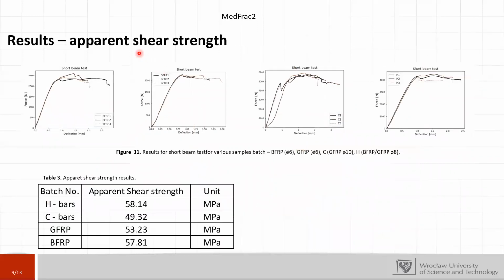Moving on, the results for apparent shear strength. So we see four graphs with the results for a different specimen batch. Here we have the basalt fiber, then the glass fiber, and here it's for the C. It's also a glass fiber, but with the greater diameter, 10 millimeters of diameter, and H is a hybrid one. And as we can see, the hybrid one exhibits the greatest apparent shear strength, 58 megapascals.